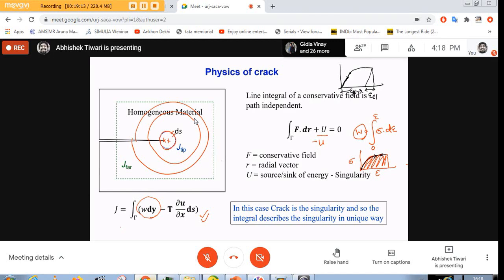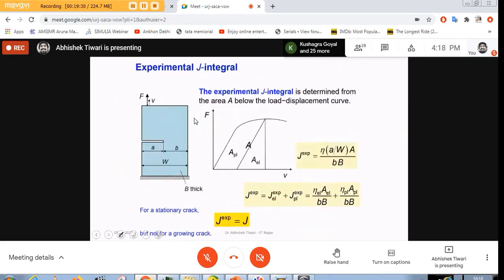So to avoid that problem, Rice said to assume this material to be non-linear elastic. This works as long as we are just loading it, but it breaks down when we unload it, and that's the problem with this. Experimentally, this integration is calculated by loading a sample, and then you get a force versus displacement diagram.